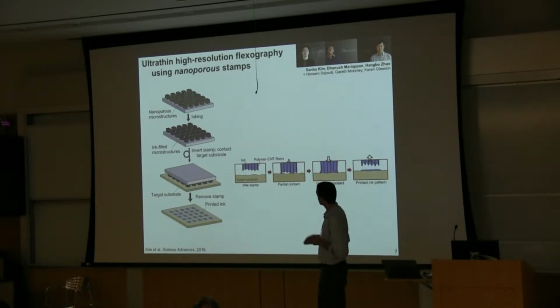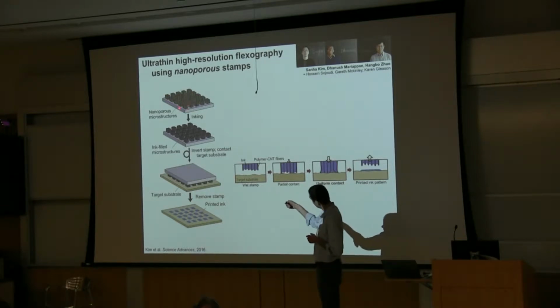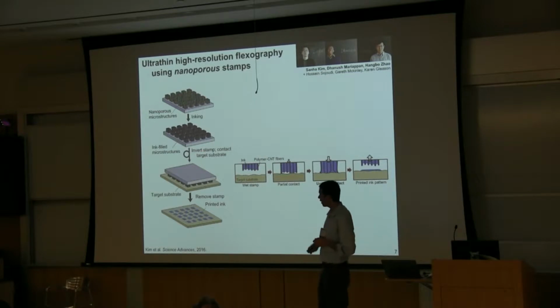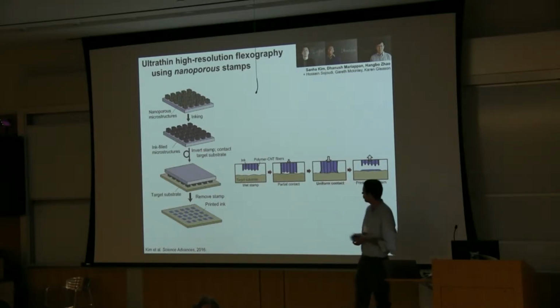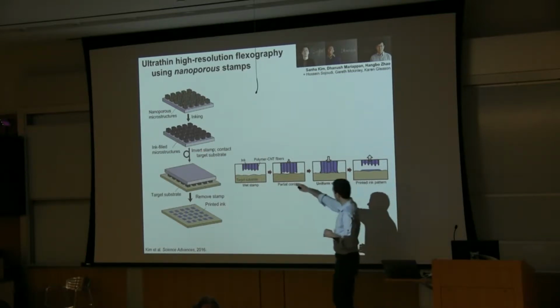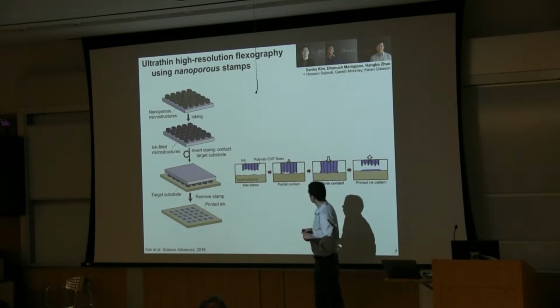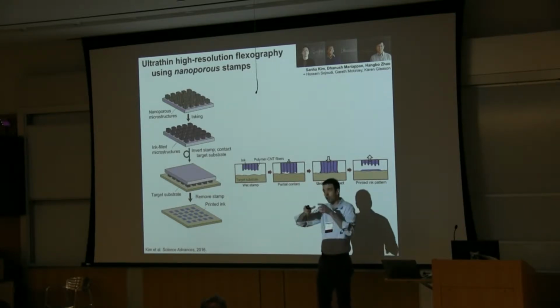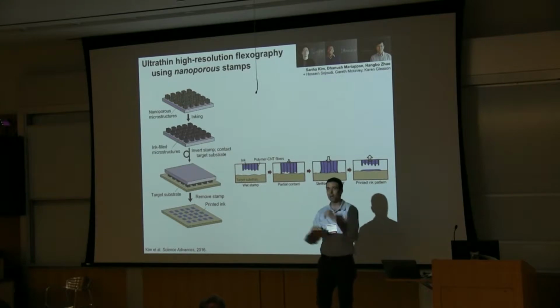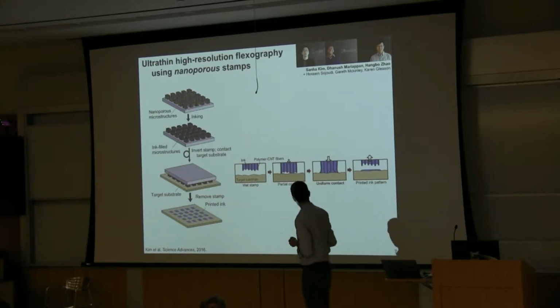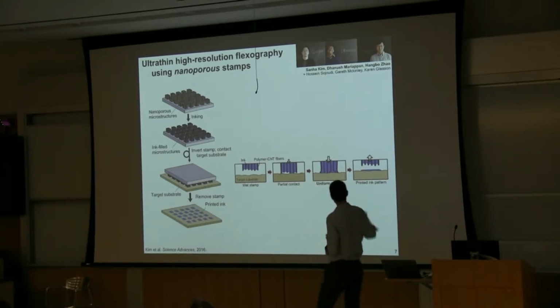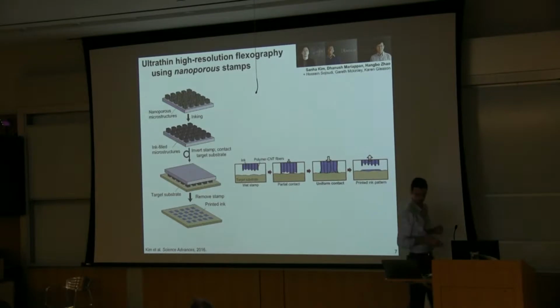These are micro-scale building blocks containing a whole lot of carbon nanotubes that make them like little sponges. You fill the microstructures with ink by capillarity, you contact, and then you print. And locally, if I give you a schematic picture of the process, imagine that each microscale feature of the stamp is like a whole bunch of little pen quills that are wetted with ink. And you can therefore make uniform mechanical contact between the stamp and your surface, and you can print a thin ink pattern, and then the solvent dries and your solid is left behind.